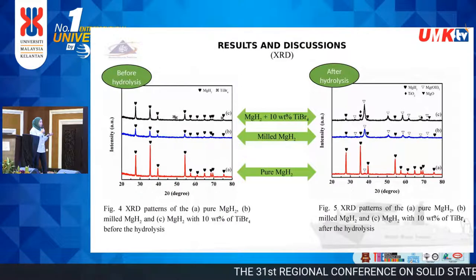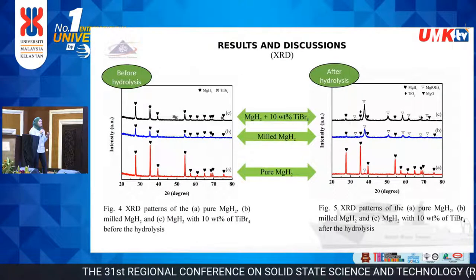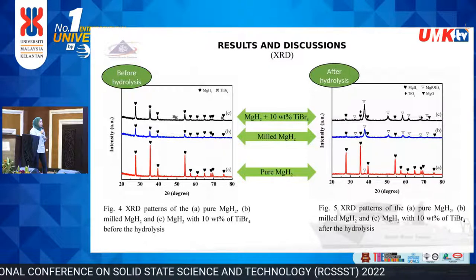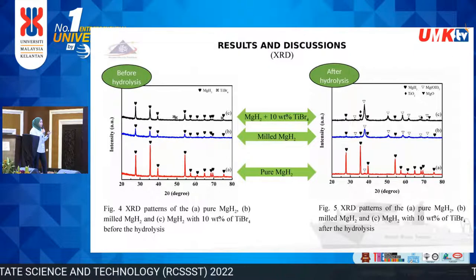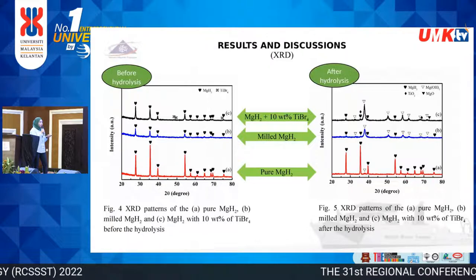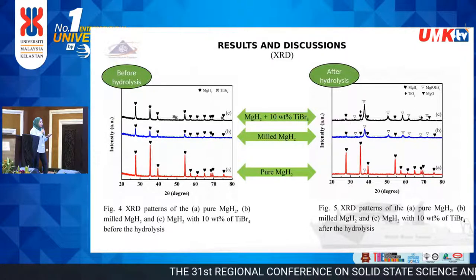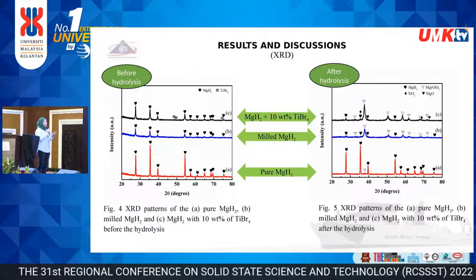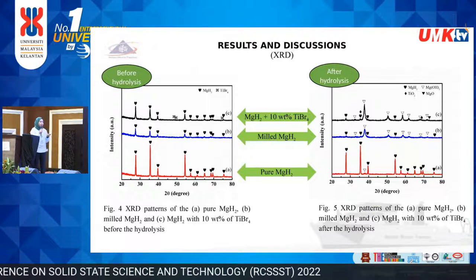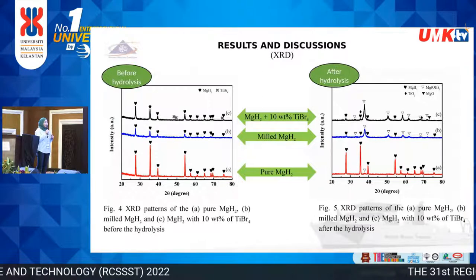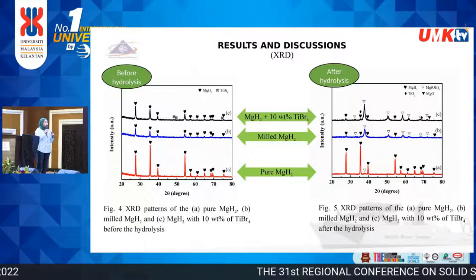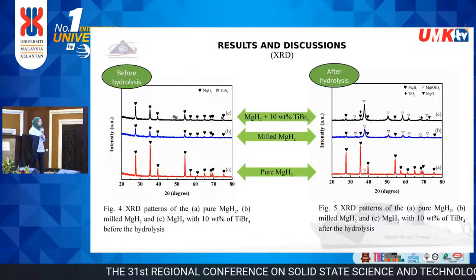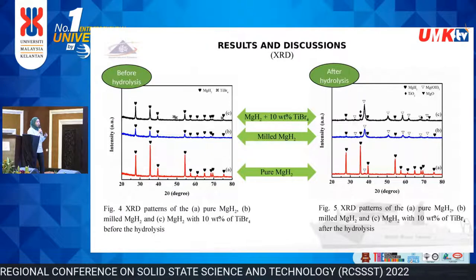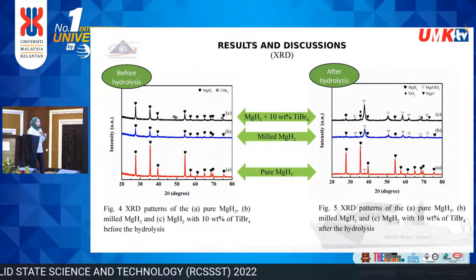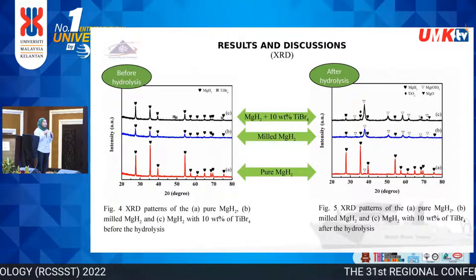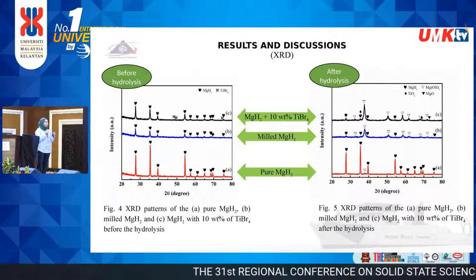For the XRD, before hydrolysis, it is to prove that the sample is pure before it can be used for the hydrolysis process. As we can see here, all the peaks belong to magnesium hydride and titanium bromide. And for the samples after hydrolysis, the XRD peaks for pure MgH2 samples, we can see that there are still many peaks of magnesium hydride and only one peak of magnesium hydroxide can be detected. This is due to the hydrolysis process only occurring for a short time. And for the ball-milled magnesium hydride and magnesium hydride with the addition of catalyst, there are many peaks of magnesium hydroxide can be seen here because the hydrolysis process has occurred for a longer time and more hydrogen is released.